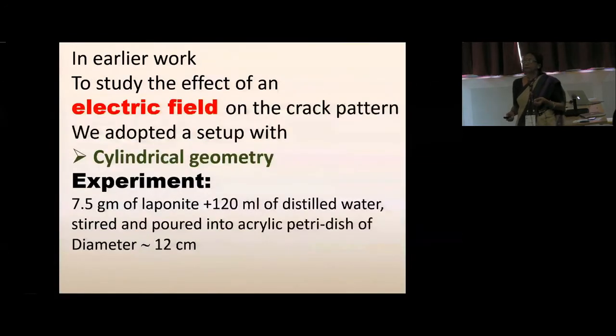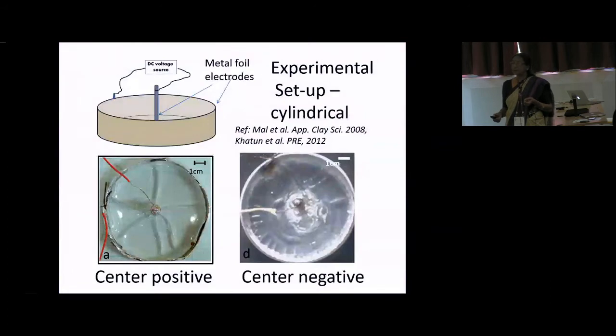Now, we have been doing this work for quite a number of years. In our earlier experiments, the setup we used for the electric field had a cylindrical geometry. And this is how we make the suspension and so on. But the setup was like this. In a Petri dish, we had two electrodes made of aluminum foil, one fitted at the periphery and one a rod-like at the center, the counter electrode. So the electric field is radial or cylindrical.